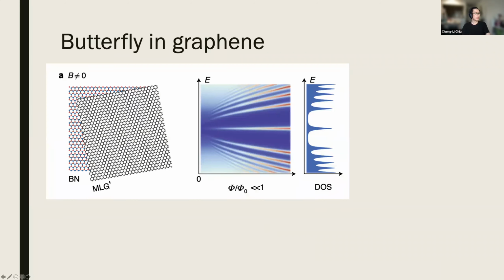So let's begin without the periodicity. If you have a monolayer graphene sitting on top of boron nitride, which is also another 2D material, it has a different periodicity from monolayer graphene, but it is an insulator. So it's more like a substrate that you can put your monolayer graphene onto. And if you don't align it, the Moiré periodicity will become very small to disappear. So you can basically consider this situation as no interaction at all. So you are just a normal monolayer graphene. And if you don't apply a magnetic field, you will have a Dirac cone, as I showed before.